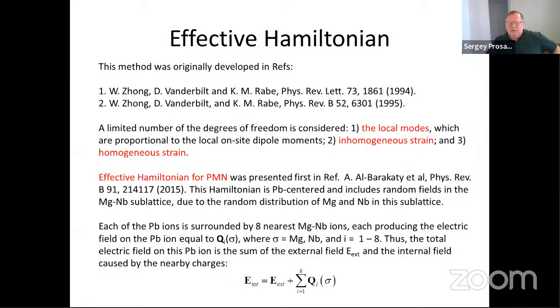So now let me start the bulk of this report, which is about calculations of this response to electric pulses. And we use the effective Hamiltonian method, which was introduced first in these two papers. I should say that this model considers a limited number of degrees of freedom, and specifically these are local modes which are proportional to local dipoles, plus homogeneous strain.